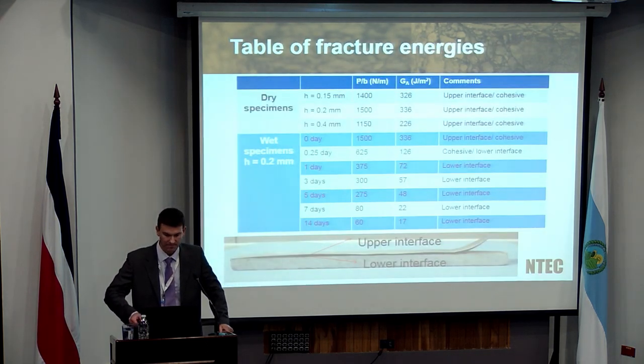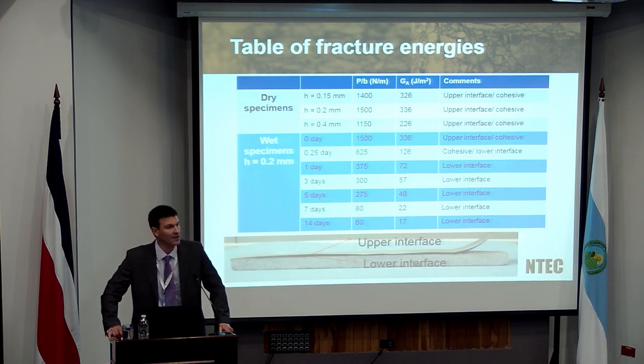So very quickly, I'm not going to go through all these values in great detail, but the top three results correspond to a dry specimen. They're the ones that we played around with the aluminium peel arm. And remember, I said we're going to use 200 microns as a standard. So the value is roughly, for the top half of that particular graph, about 1,500 newtons per meter. Or if you look at the fracture energy, about 350, 330.